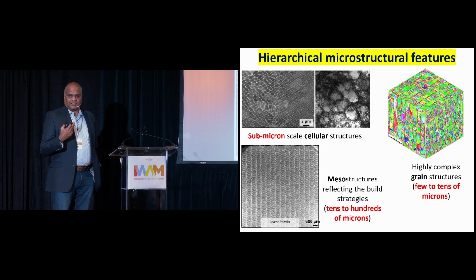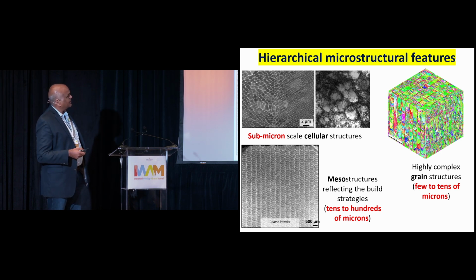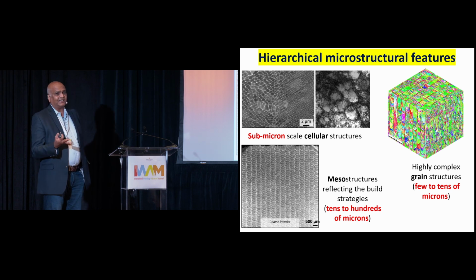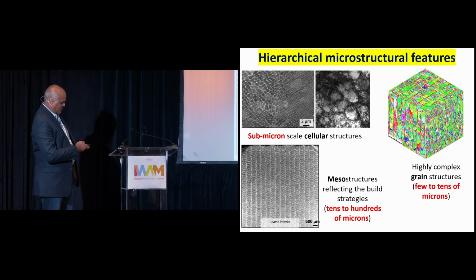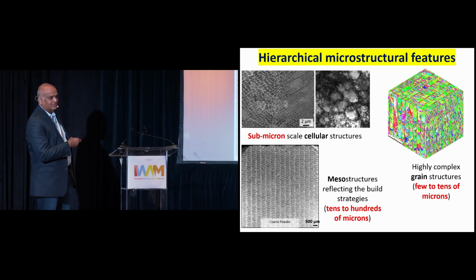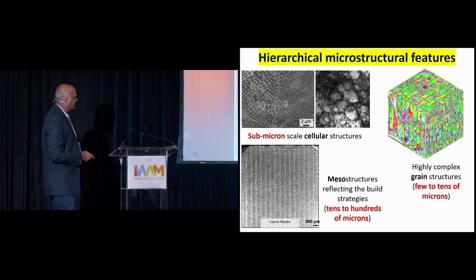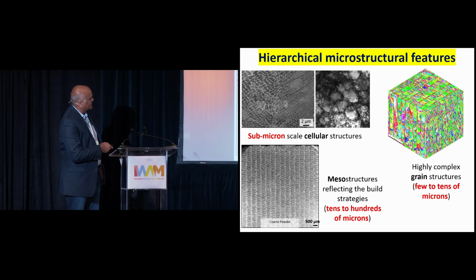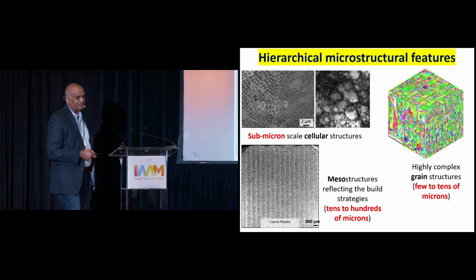When you 3D print a metallic material using laser powder bed fusion technique, you get a hierarchical microstructure - hierarchical structure features. At the sub-micron scale, you have cellular structures, and if you do TEM on it, you'll get very high dislocation density decorating the cell walls. From few to tens of microns, you get very complicated grain structures. At a much larger scale, you have these meso-structures, often hundreds of microns in scale. So you have these features, and all of them could influence your mechanical response, and I will try to illustrate that.